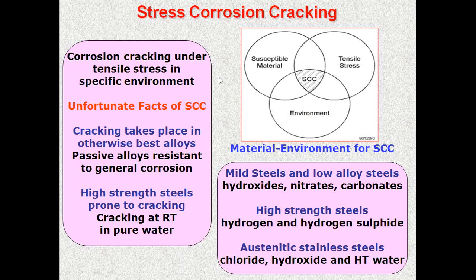Stress corrosion cracking is another major type of corrosion, which is mainly due to the combination of tensile stress and a particular specific environment. It is a combination of tensile stress under a specific environment, with a material like stainless steel, which is susceptible to stress corrosion, and it undergoes stress corrosion cracking. And there are different combinations: high strength steel, you have hydrogen and hydrogen sulfide; mild steel, you have hydroxide, nitrate and carbonate; and austenitic stainless steel, you have chloride, hydroxide and high temperature water.